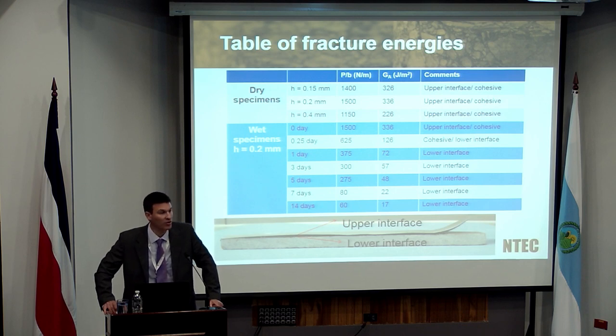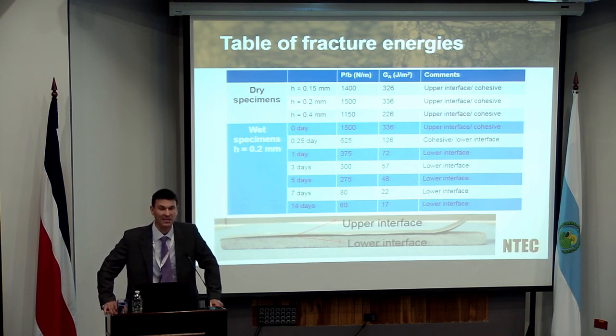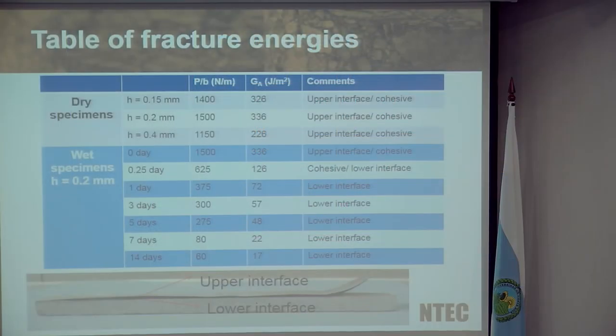And then the bottom seven results correspond to our moisture-conditioned behavior, where, as I mentioned earlier, we might have a relatively short amount of moisture conditioning for 6 hours in a water bath, all the way through to about 2 weeks or 14 days. And again, we're now starting to see not only a reduction in our fracture strength, in other words, the start of moisture damage or peeling or stripping of our material, but also we have the ability to identify the exact failure mechanism in terms of the location of that particular failure. So it's moving from a cohesive type failure within the adhesive or the bitumen all the way down to an interface failure between the aggregate and the bitumen.